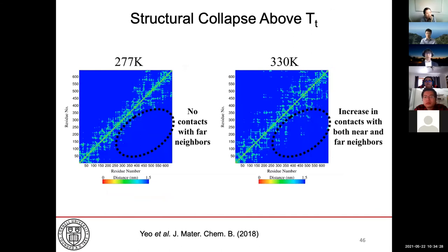And we also plot the contact maps before and after the structural transition. And a contact map is basically a matrix which shows which residues are close enough to be in contact with each other within the protein. And it shows that the molecule basically remodeled itself after the structural transition and increased the number of contacts with neighbors that are much further away. And therefore, it became much more compact in structure.